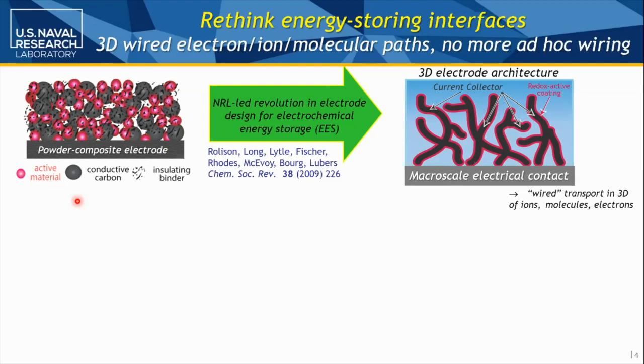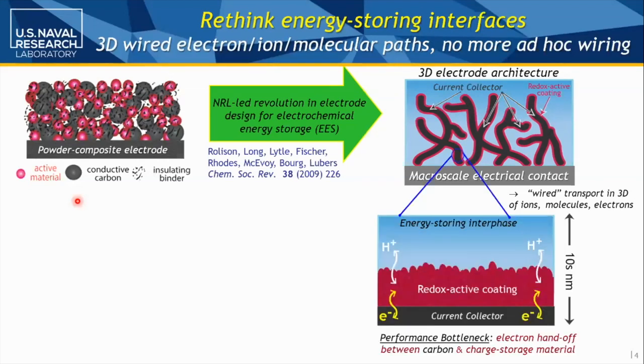So now we're thinking about, I need to wire electrons, I need to wire ions, I need to wire molecules to really get current. And I need a lot of area, so I've got enough, if you will, mass to store energy. Those two things need to be distinct. So if you're looking at a more bird's eye view, you've got your macro scale current collector, we can't see anymore. We've got our black sort of architected current collector, a redox active coating, and we're talking to where the ions and electrons need to live with short distances. You notice that scale bar, tens of nanometers, not tens of microns, as in a classic battery material.